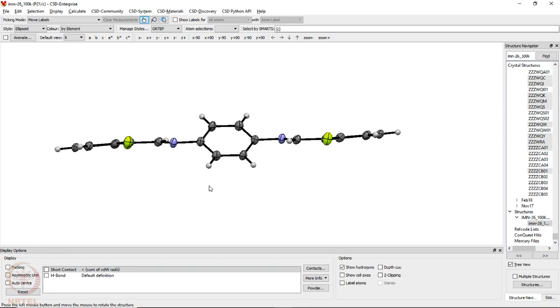In this process, the solute-solvent interactions are different based on what the solvent is and what the solute is. So, what may happen is that from a given bulk sample of a particular crystal structure of a particular crystal system, on dissolving and recrystallizing, it may give you a completely different three-dimensional packing. This new packing may or may not contain a solvent, and that structure is what we have determined using the single crystal X-ray diffraction method. One can ask, how do you know that this structure that you have determined from a single crystal is the same as that of the powder X-ray diffraction data?